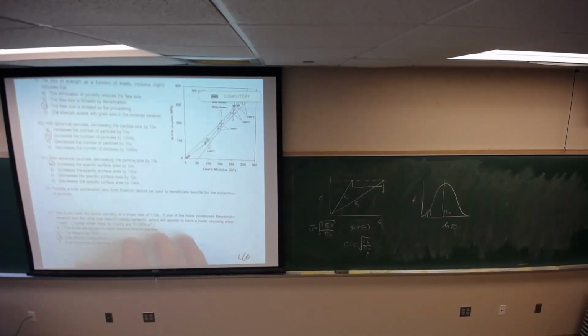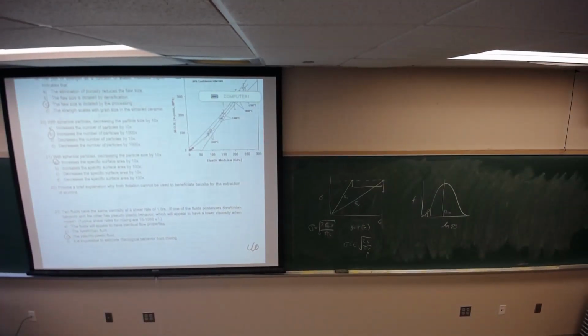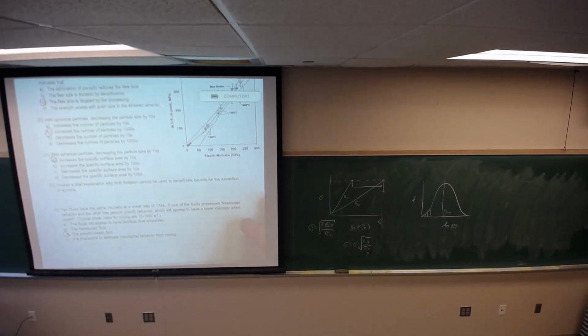Good? Two fluids of the same viscosity, shear rate of one fluid possesses Newtonian behavior, the other has pseudoplastic behavior, which would appear to be lower viscosity. Typical shear rates are 10 to 1,000, so the pseudoplastic fluids appear to have a lower viscosity. Good? Okay?